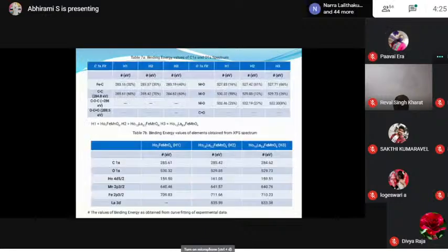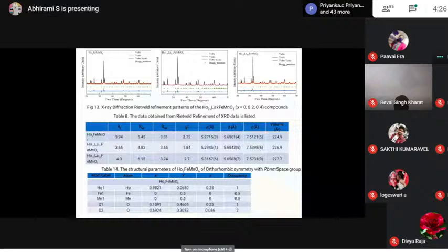These are all the binding energy values of the C1s and O1s spectra of my prepared compounds, and the binding energy values of the elements obtained from the XPS spectra are shown here. Another characterization technique used is XRD. These are all the spectra of the pure and La doped Ho2FeMnO6 compounds, and these are the obtained Rietveld refinement values. Then the structural parameters of the pure and La doped compounds are shown here.